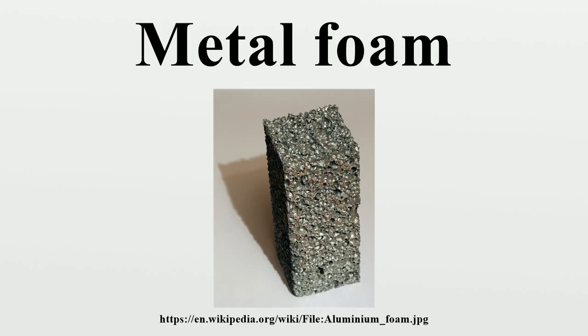Composite foams formed from hollow beads of one metal within a solid matrix of another, such as steel within aluminium, have been formed in a laboratory, and are showing 5 to 6 times greater strength-to-density ratio, and over 7 times higher energy absorption than previous metal foams. Stochastic and regular foams. A foam is said to be stochastic when its porosity distribution is random.